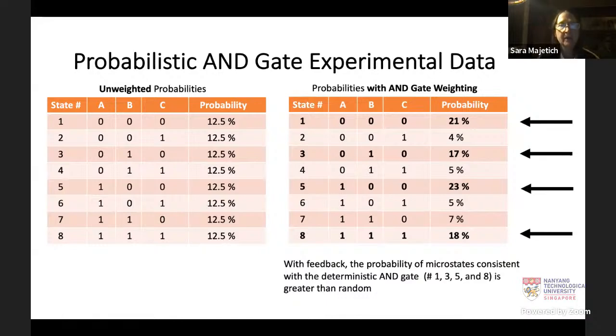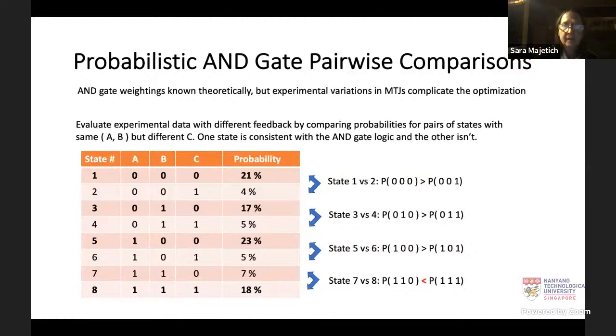But our probabilities do change, and we do see qualitatively consistent behavior of favoring those 4 states over the ones with the wrong value of C. But it's not 100%, it's not 90%. So we're getting statistical differences, but it's not as much. And so that means that you have to average over a longer period of time, more cycles, in order to get good statistics for your process. And so again, we've been able to look at these statistics.